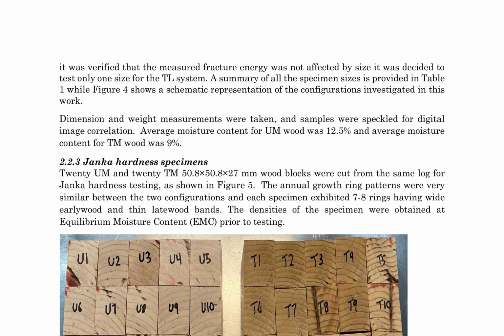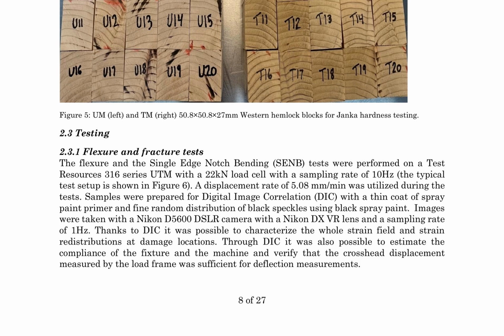Flexure and single-edge notch bending, SENB, tests were performed on a Test Resources 316 series UTM, utilizing a 22 kN load cell with a 10 Hz sampling rate. The typical test setup is shown in Figure 6. A displacement rate of 5.08 mm per minute was employed during testing. Digital image correlation (DIC) analysis was facilitated through a thin coat of spray paint primer and a fine random distribution of black speckles. Images were captured with a Nikon D5600 DSLR camera and Nikon DX VR lens, with a sampling rate of 1 Hz. DIC analysis enabled the characterization of the whole strain field and strain redistributions at damage locations, as well as the estimation of the compliance of the fixture and the machine. This experimental setup allowed for a thorough investigation of the mechanical properties of untreated and TM wood specimens.